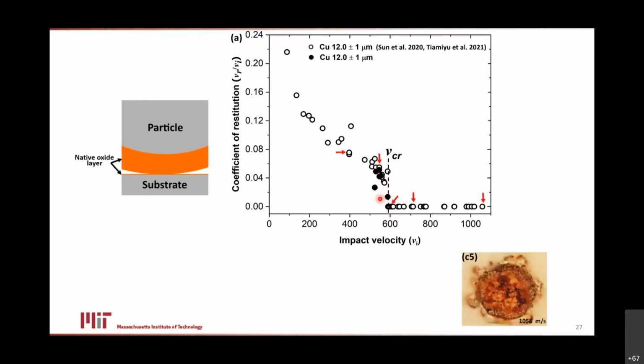Let me start with one observation. I'm going to start with really high velocity here. This is a copper particle hitting a substrate. Bear in mind again that the copper has a big, thick oxide layer on it, and that's what you're looking at here. When you stick a particle to the substrate and look at it in the confocal microscope, this coloration here, this bright orange, is the thick oxide, so it is visible in this form of microscopy. Compare that to a freshly prepared substrate, which is almost oxide free. This is bare copper, and this is the thick oxide. So that's what oxides look like in the microscope.